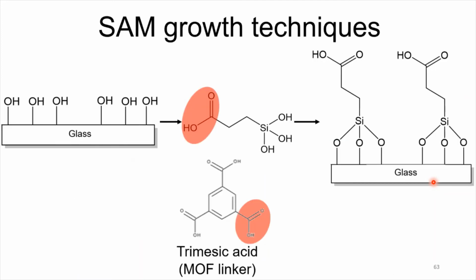And what I didn't mention here is the monolayer that we are going to use in these 2 cases is this molecule here, this silane in the middle. So very much as we did in the magnetite device, we use the silane group to attach to the glass, while we have this free group that reminds you of the linker attachment, functional group.